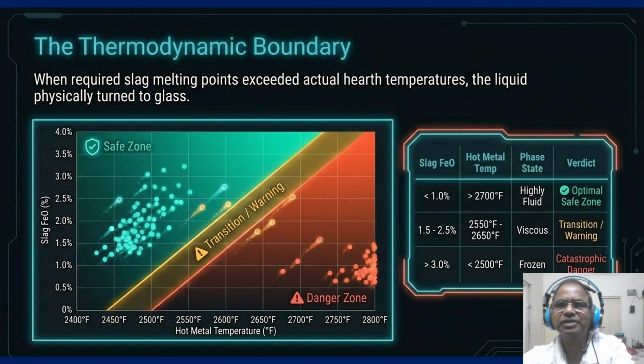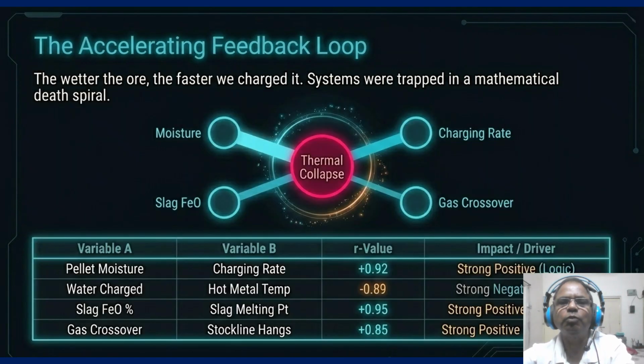So this disaster was not a linear progression, it was an accelerating feedback loop that trapped the operators. So coming to the accelerating feedback loop. This is the death spiral. Look at the constellation plot in the center. Moisture, charging rate, gas crossover and slag FeO are all feeding into the thermal collapse.